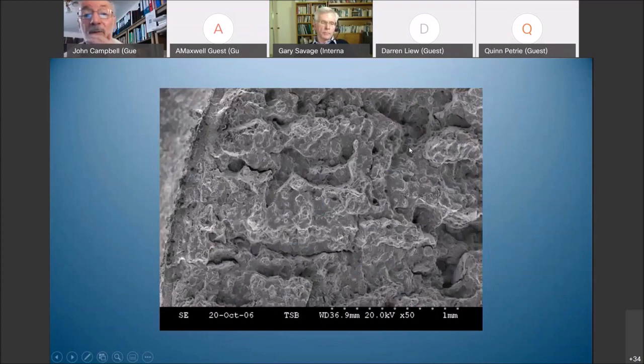Here we are again with the same fracture surface. It looks chaotic, but in fact, these are dendrites we can see with an overlying oxide, which is the bifilms again. And what's more, you can see cracks at right angles going into the structure. And this is again typical of bifilms because they're not just straightened out on one plane, they're straightened out on planes at right angles. They're not like ordinary planar engineering cracks. They go off in all directions. So this is a typical bifilm failure.